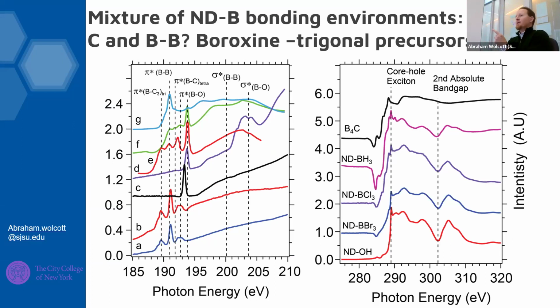Again, we go to the synchrotron and we go ahead and we look at our two edges. On the left-hand side, we're looking at boron. And so you're only looking at boron at that time. On the right-hand side, you're only looking at carbon. Again, we go ahead and use a combination of our samples, BBr3 and BCl3 related samples, and then compare those to our controls. This is boron carbide, elemental boron, and our other controls, and this is boric acid right here. And so what we see is a mixture. It's heterogeneous. Again, it kind of looks like boron carbide, but not exactly. You've got evidence, again, of a boron-carbon bond, boron-boron bonds, and this trigonal and tetrahedral bonding environment.